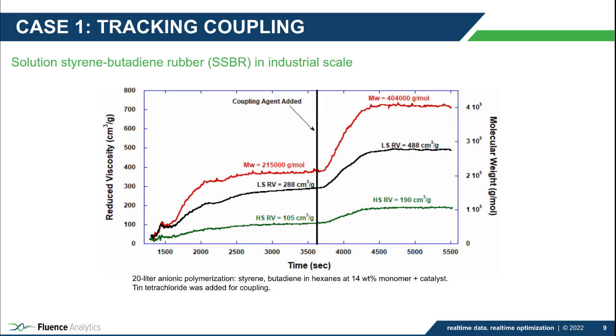Now going into some case studies. For solution styrene butadiene rubber industrial production, ACOMP allows for identification of the coupling reaction in real time through three main calculated parameters from the multi-angle light scattering and the viscometer units: molecular weight, and low and high shear reduced viscosity. As we can see on the plot, this reaction has two main phases.